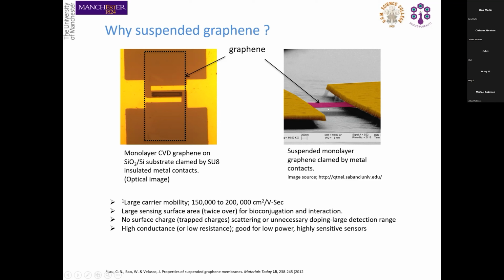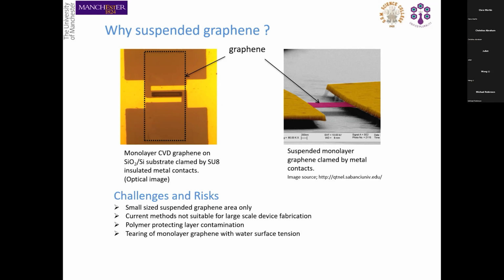And of course, we get to double the surface area. So there's a surface on top and a surface on bottom. This is very important for interaction with the biomolecules or gas molecules in terms of sensor technologies. Also, because of no interaction from the surface, no scattering sites, there's a high conductivity between these two electrodes because of the graphene. So suspended graphene provides a lot of applications when you want to make very highly sensitive biosensors or gas sensors. But there are challenges.